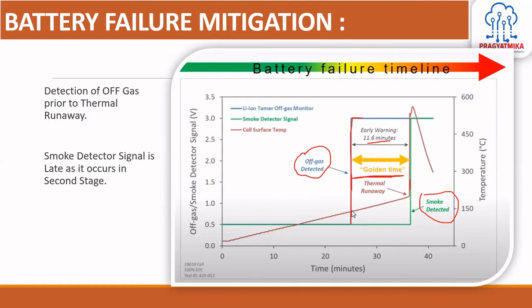If at this stage the timer detects this, and generates the signal for the disconnection of the charging or discharging system from the battery pack, the temperature could be lowered, because once the off-gas event has started, it means the thermal runaway process has started, and temperature is increasing. As you can see, the cell surface temperature is increasing constantly. And if I have not put any kind of timer signal onto this, and even after detection of the off-gas events I have not taken any mitigation step, then further the smoke will come, and at this time the cell surface temperature will rise drastically,